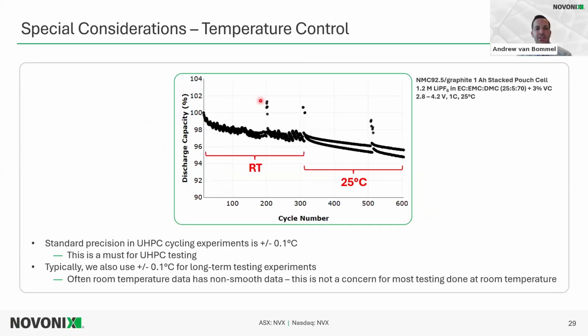So another special consideration for cell testing is temperature control. Here's showing the discharge in long-term cycling. This is 1C cycling. At room temperature, we see a lot of wobble because there's a lot of temperature variation. This is HVAC controlled, so it's not too much, but we see some variation. And this isn't too much of a concern because if we're comparing one cell to the next, and the cells are sitting next to each other, they'll experience the same temperature variation and the same conclusions can be drawn.